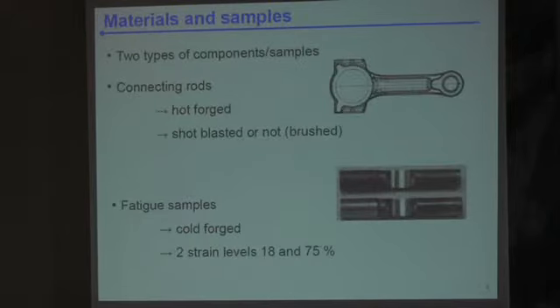So there are two types of components, or two types of samples that we have used. Some samples we have extracted from forged parts, connecting rods in that case, and they are extracted directly from the components. They've been hot forged, and some of them have been shot blasted. I'll come back to the shot blasting process after. And those which are not shot blasted are just brushed to remove the scales from the forging process.